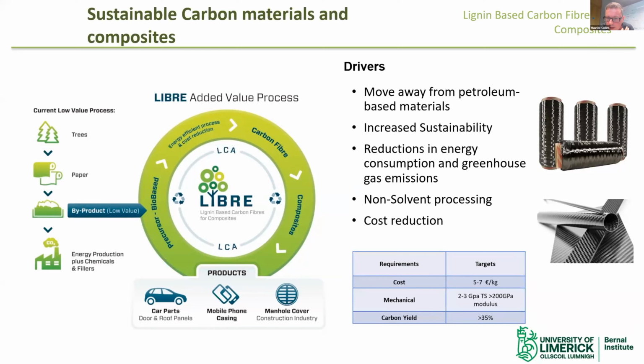So the reason that we were doing this, the drivers were that it's a move away from petroleum-based materials, increased sustainability, reductions in energy consumption, greenhouse gas emissions. We were using a non-solvent processing technique, so we were spinning these fibers, but we didn't spin them using solvents. We spun them using melt spinning, so we took solvents out of it. Conventional carbon fibers are made from fossil-based PAN materials, and they're spun using solvents. As well as being fossil-based, they also use solvents, and they also use extremely high temperatures. So that's why you might remember one of the earlier presentations showing that there's a huge carbon emissions associated with carbon fiber production, and that's why.